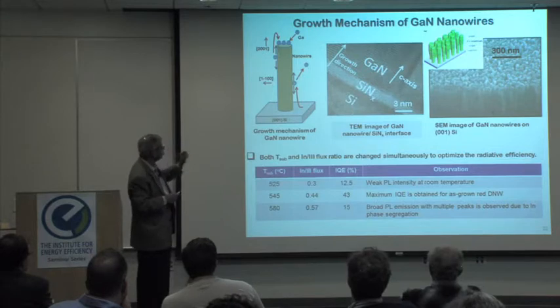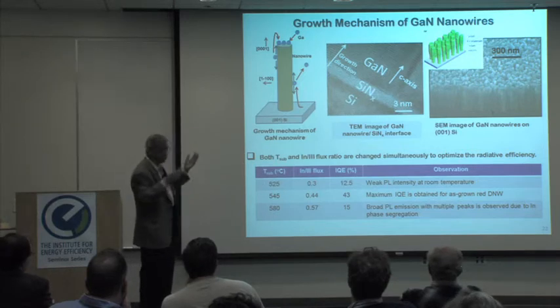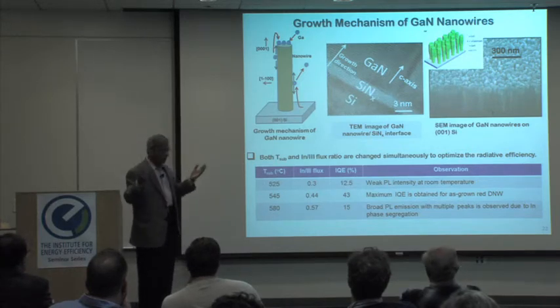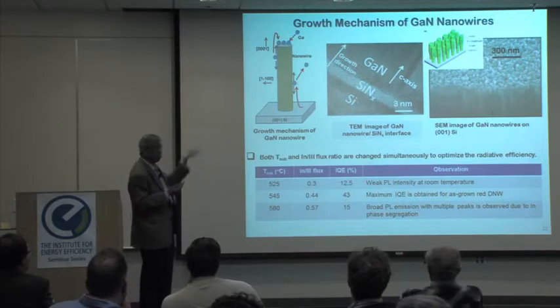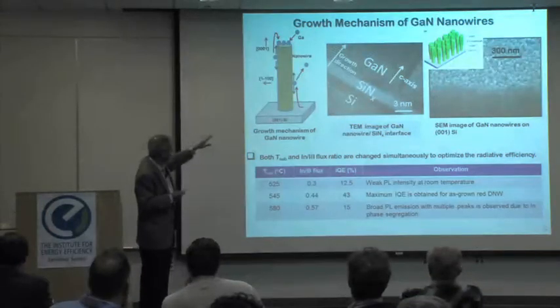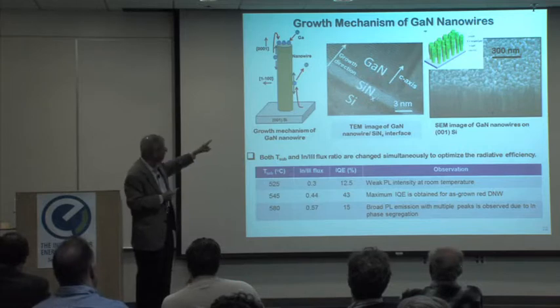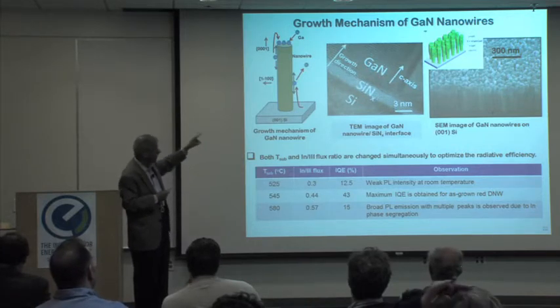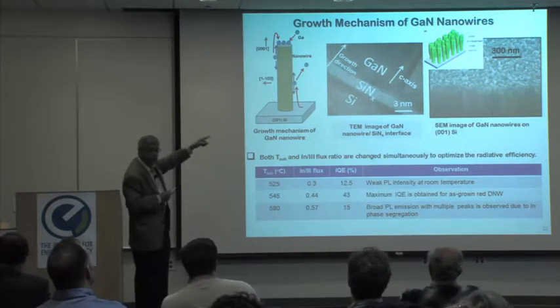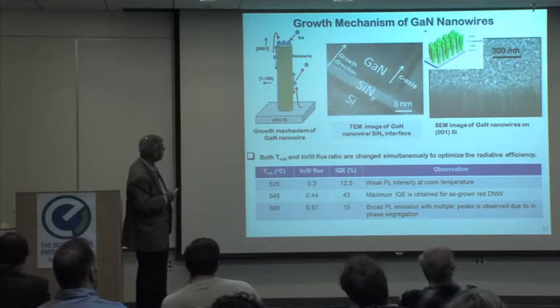One, it removes the epitaxial constraint of the substrate, and therefore you can grow it on 001 silicon, you can grow it on 111 silicon, on other templates, whatever, you always grow these nanowires because there is no epitaxial constraint of the substrate. The silicon nitride also greatly reduces the 13.5% misfit on the substrate, greatly reduces the defect density at that interface, unlike bulk, unlike two-dimensional growth.